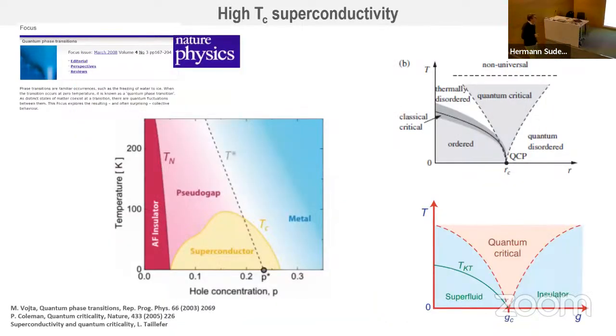But actually, there is one big question. It is, what is the origin of this phenomenon at high temperatures? And in particular, what is the role of electron correlations in this? So electron correlations are the ones which are responsible for the high critical temperature superconductivity, and we don't know how to describe them and how to manipulate them in some sense. So this kind of phase diagram gives us some clue. So we have a superconductor, and then we have strange electronic excitations which change as a function of some tuning parameter. So this is very nice, but these materials are relatively complex.